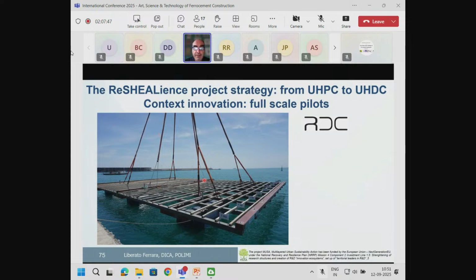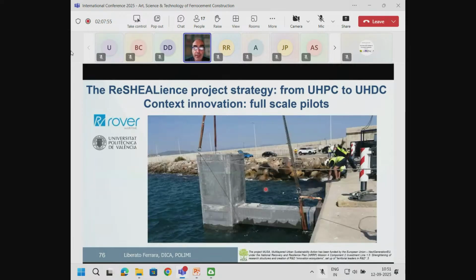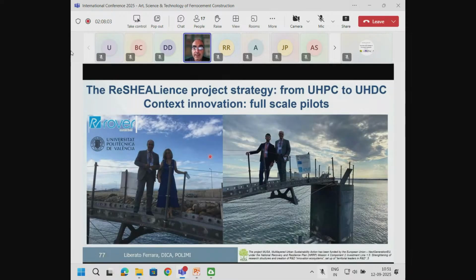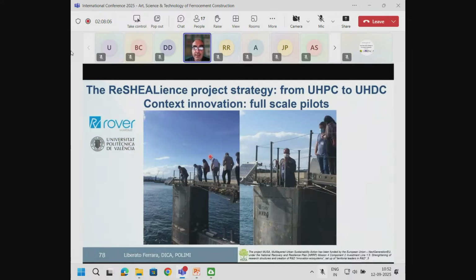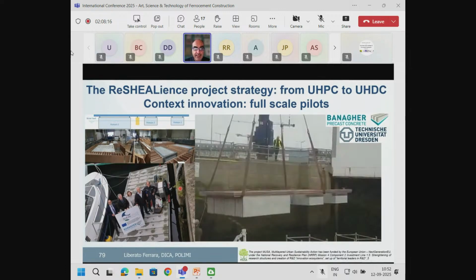partners. This is a raft for mussel farming. These were pre-stressed UHPC beams, very thin cross-section. This was a floater for a wind tower with walls with just a few centimeters thick. So really very interesting application, and you can see also some other pictures. This floater follows obviously, and you can go and inspect it. There are pilots which are really installed in the real environment and tested.